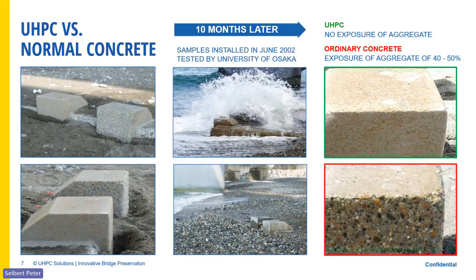It also has a very great resistance against abrasion. This is an older slide, basically where you could take a regular concrete material that was exposed to marine environments, that's being hit by waves and water all the time. So you have a regular concrete over here, and then you have a UHPC material beside it. And you can see, within 10 months, you already see the regular concrete starting to deteriorate, whereas the UHPC looks beautiful like on the first day.